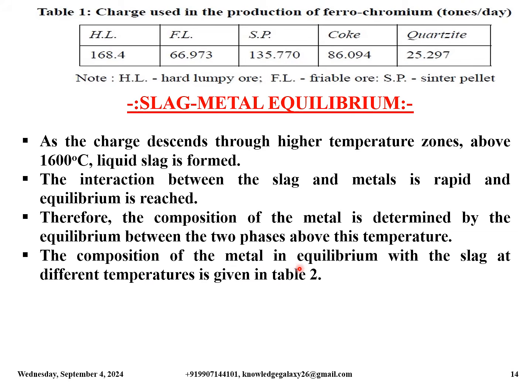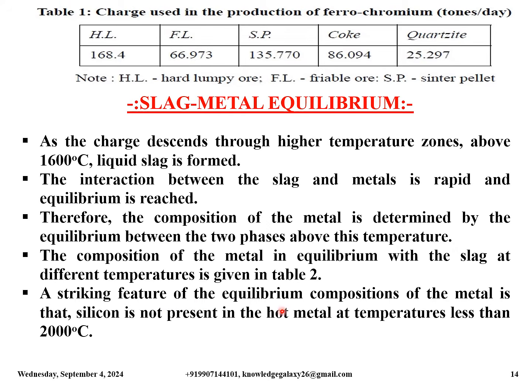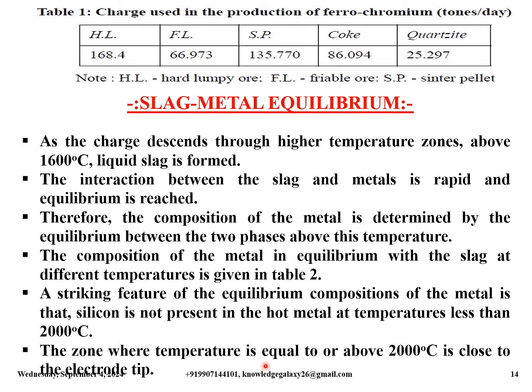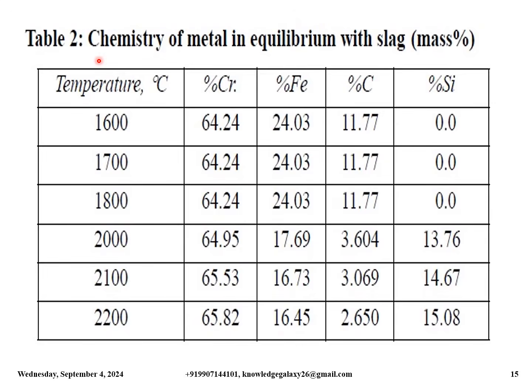The composition of the metal in equilibrium with the slag at different temperatures is given in Table 2 in the coming slide. A striking feature of the equilibrium compositions of the metal is that silicon is not present in the hot metal at temperatures less than 2000 degrees Celsius. The zone where temperature is equal to or above 2000 degrees Celsius is close to the electrode tip. So this is Table 2, which gives the chemistry of metal in equilibrium with slag, and it is in mass percentage. You can pause the video and observe the different contents of the table.